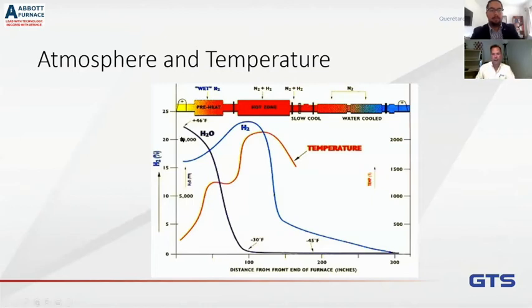Okay. So remember what we said, we loaded the parts at the front of the furnace. And then as we went through, we heated the product up and then we reduced the oxides. Well, what's happening is we put our hydrogen and nitrogen in the back and they're flowing towards the front. That hydrogen will actually react with the oxides on the surface and form water. So what you see is, you notice how the amount of water goes up as you go towards the front of the furnace, and the amount of hydrogen goes down slightly. And that reaction is a function of temperature.